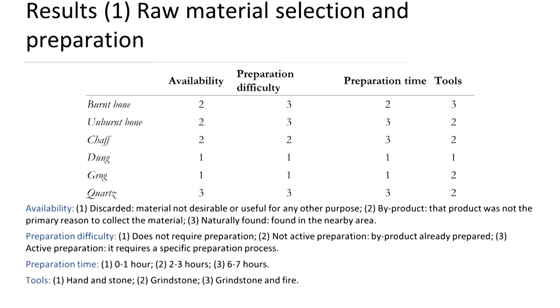From the first stage of raw material selection and preparation, it was observed that they actually behave quite similar. The only thing was the time necessary to prepare the tempering materials. While unburned bone, quartz, and chaff were very time-consuming to prepare, at least 6-7 hours, the others only require less than an hour.